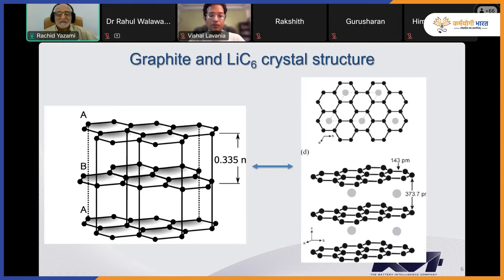When lithium is intercalated into graphite, the graphite material changes in color. So there are two major colors that are known. One is the blue color, which is half lithium for every six carbon, or LiC12. This is blue color. And the LiC6 structure is a gold color. And actually, when I discovered the graphite anode the first time, I opened the electrochemical cell and I found that the graphite turned from gray or black color to gold color. And I understood at that time, yes, I was able to intercalate for the first time lithium, only lithium without any solvent, into the graphite structure. Next slide, please.